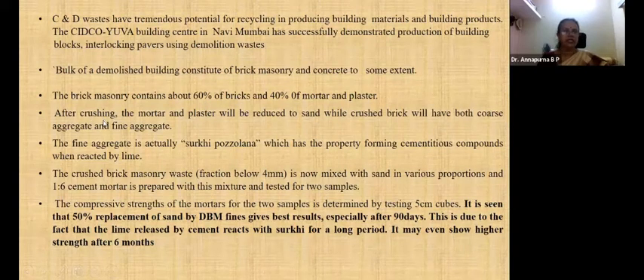After crushing, this mortar and plaster will give both coarse aggregate and fine aggregate. The fine aggregate obtained from this mortar and plaster can be used as surki pozzolana, because the reacted lime content is present in the mortar and plaster. So this fine is actually surki pozzolana, which has the property of forming cementitious compounds when reacted with lime.